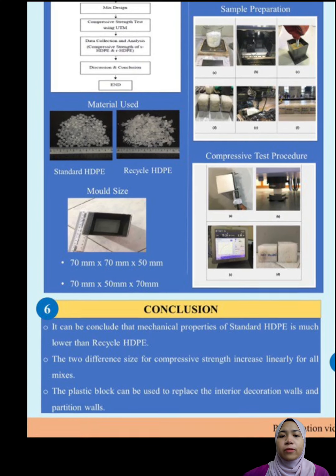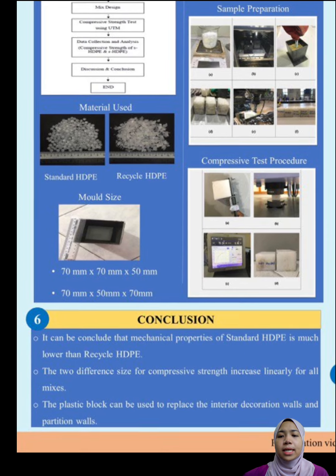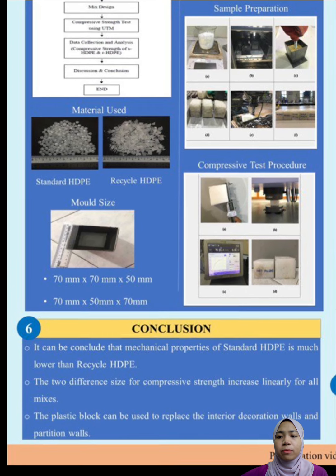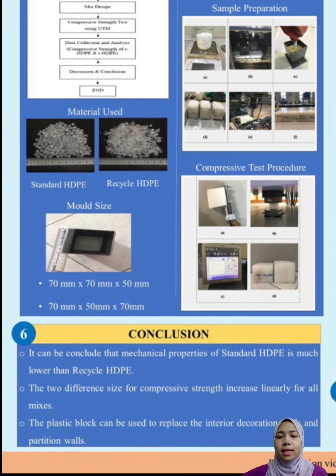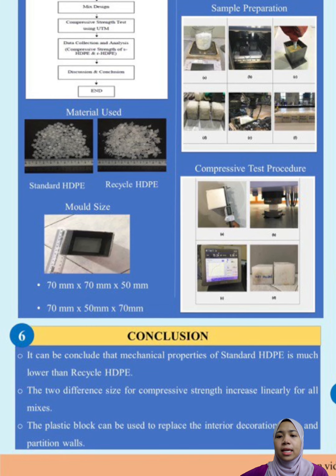The conclusion from this study is that the mechanical properties of standard HDPE are much lower than recycled HDPE. Secondly, the compressive strength for the 2 different sizes increases linearly for all mixtures. Lastly, the plastic block can be used to replace interior decoration walls and partition walls as a construction material